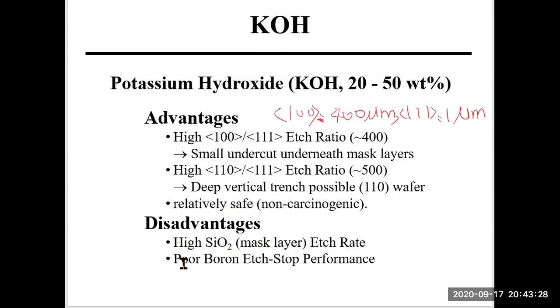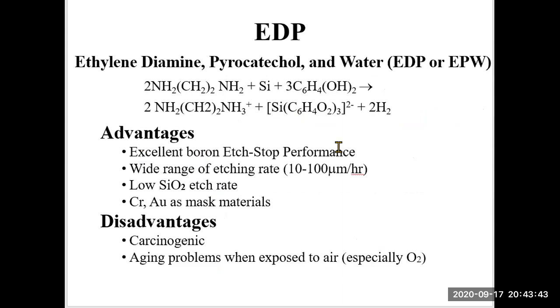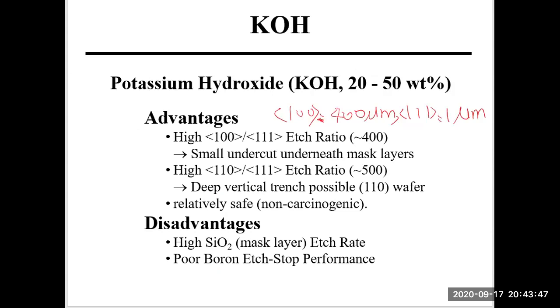Another disadvantage is poor boron etch stop performance. It's not as good as EDP, which has excellent boron etch stop performance. So if you want to choose an etchant that will use a boron etch stop, which one do you choose, KOH or EDP? Typically, we choose EDP, because EDP has a much better boron etch stop performance. I think I will stop here for today.